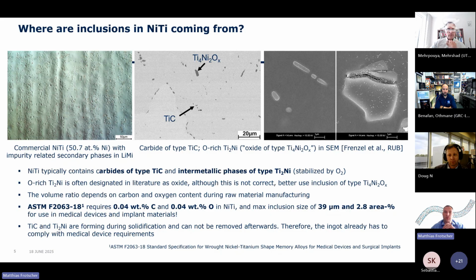The carbon can be introduced, for example, through a graphite crucible material, and you have to keep in mind that there's a difference between the purity of the material, which is pretty much fixed after melting when you have your ingot, and the inclusion size and distribution, which can subsequently be affected by forming processes such as hot or cold working. You can see examples of the two relevant inclusion types in Nitinol in these images. We call these titanium carbides, so of type TiC, and intermetallic phases, so Ti2Ni, which can solve a lot of oxygen. In literature, you sometimes find these designated as oxides, although technically that's not really correct.